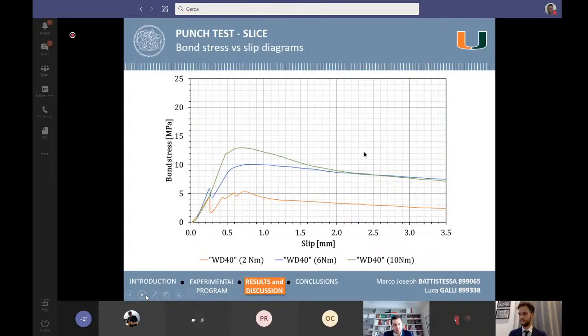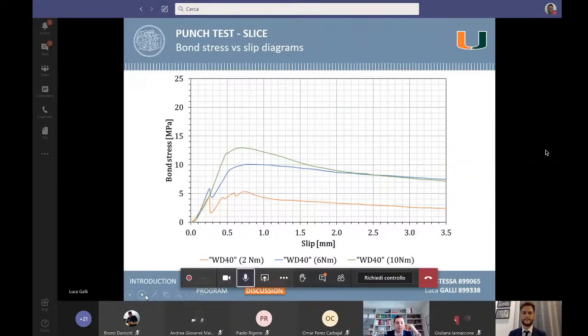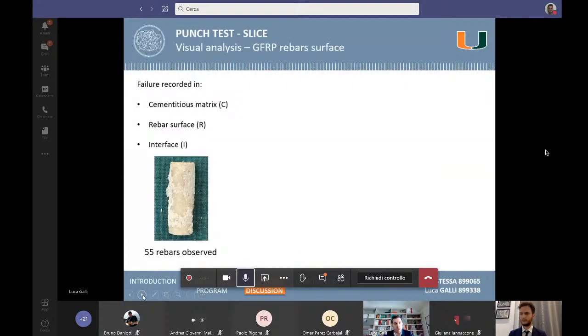In the samples partially splitted, we can observe that after the discontinuity, there is a further increment in the bond stress. That's why in such cases, the crack propagates until it meets the opposition of the confinement action provided by the steel clamp. In fact, increasing the tightening torque applied, the discontinuity becomes shorter and the maximum bond strength becomes higher. At the end of the punch test, a visual analysis of the GFRP rebar surface has been carried out to evaluate the failure mode.